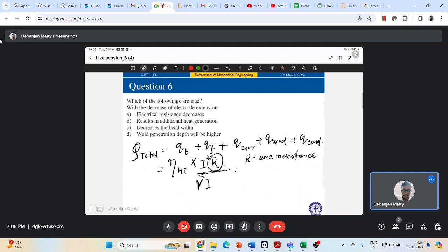If your arc is short in nature, what will happen? There can be some short circuiting during the metal transfer. If your arc is large or long enough, what will that do? It lacks direction, it lacks intensity. So there will be scattering during your weld formation, right? There will be formation of undercuts. So it will form some undercuts like this. So these are called undercut. And this happens if your arc length is very large, and the bead appearance is